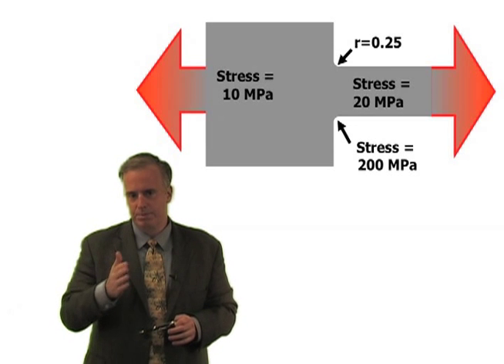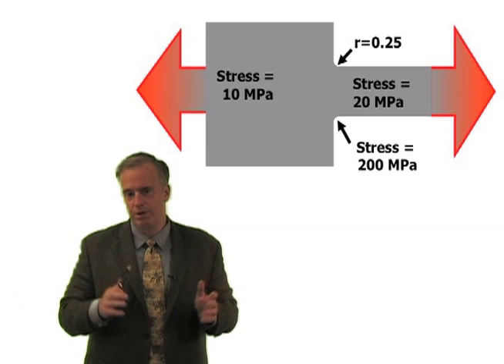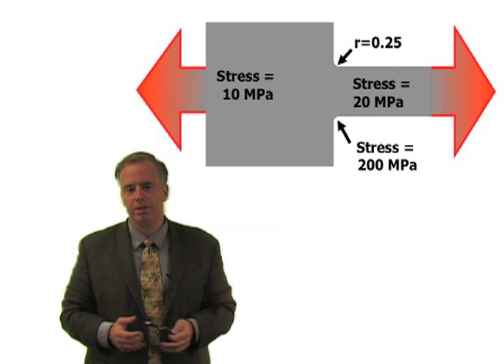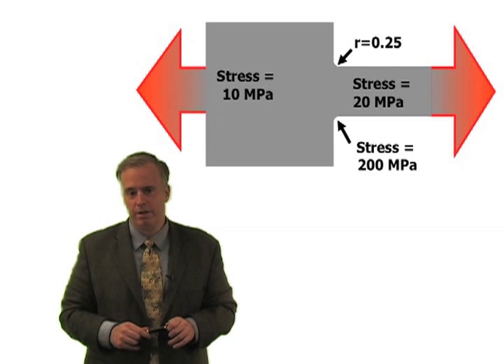We're going to do it with a specific grinding operation. We're going to plunge in with a certain grit wheel. And what that's going to do is that larger radius is going to reduce those stress concentrations. And you're going to have much less likelihood of cracking that part.